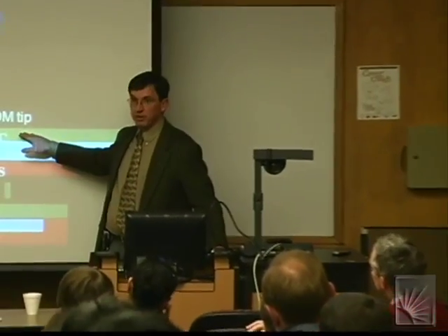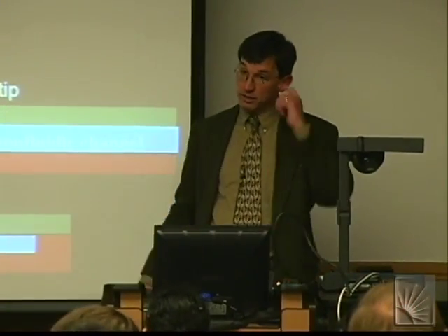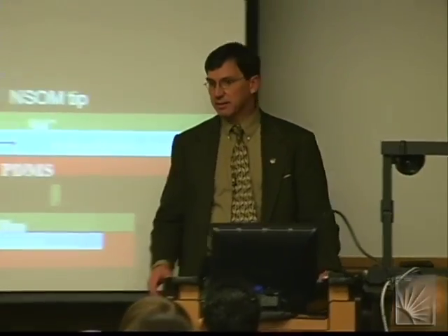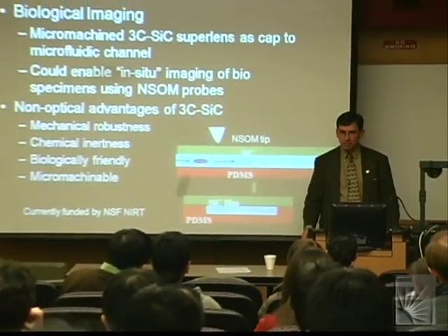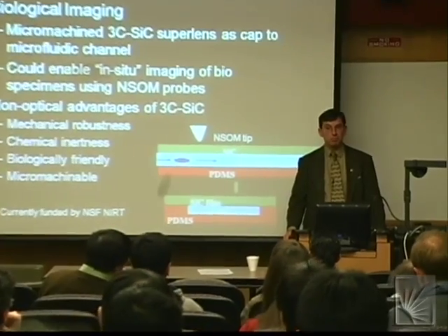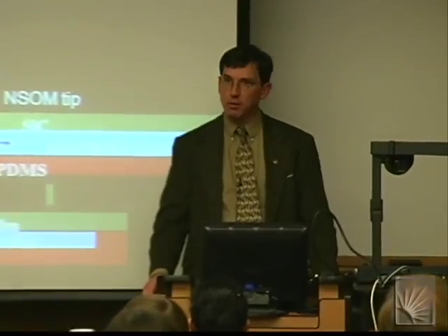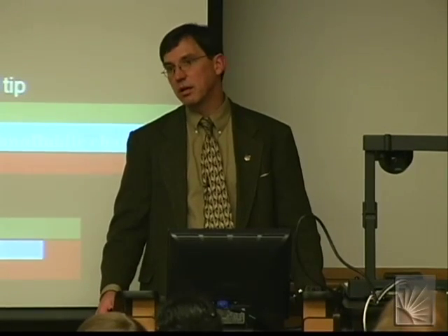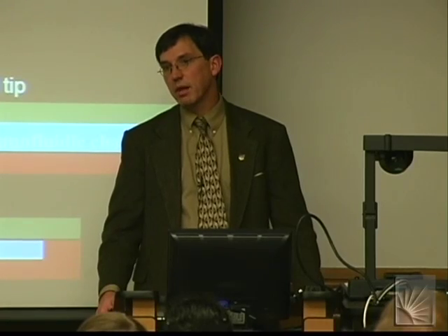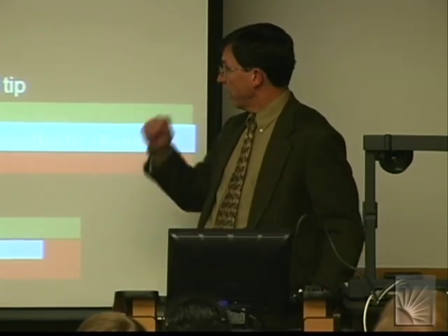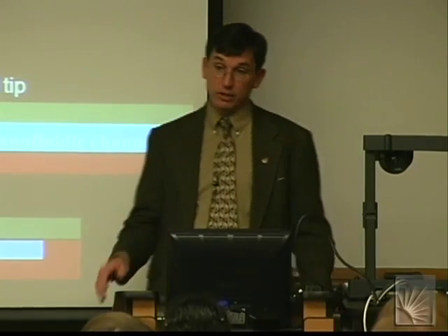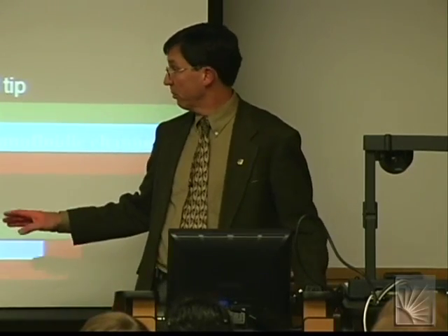Any other questions? Well, I've got one. Go ahead. What kind of silicon carbide film is this? On this particular one, this would be a 3C film grown on a silicon substrate. We call it an epitaxial film. It's a heteroepitaxially grown film. It's single crystal for the most part, with lots of defects in it. Does that require a typical special thickness? That's a good question, and that's actually one of the things we're looking at in this NIRT program.